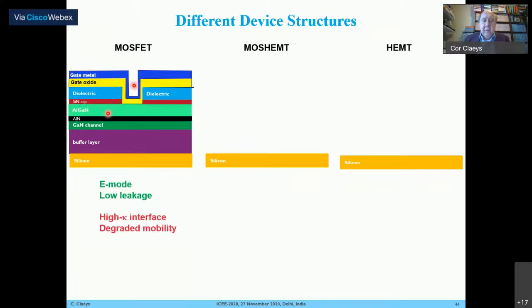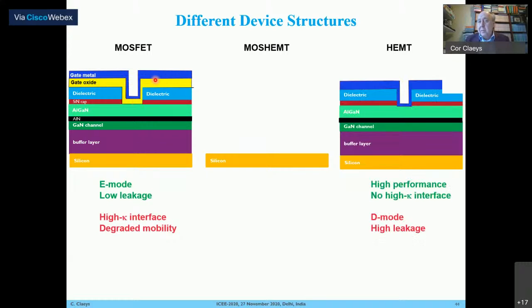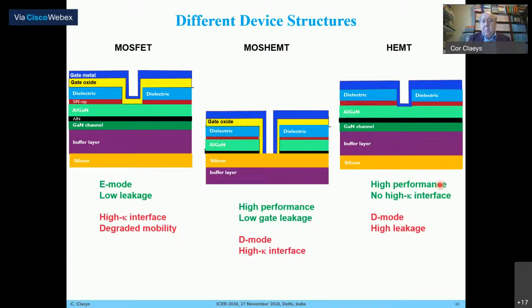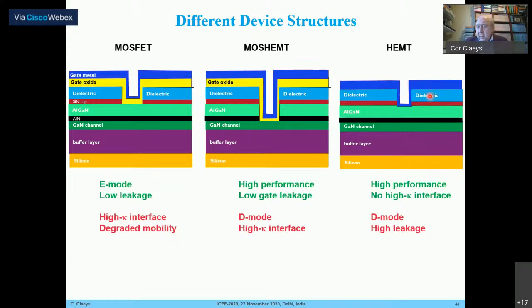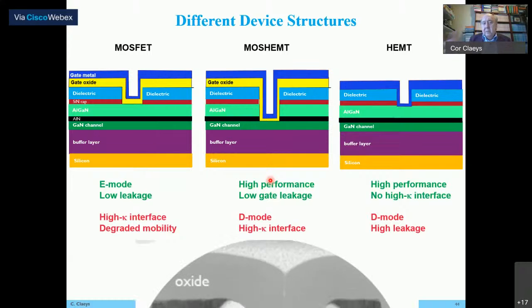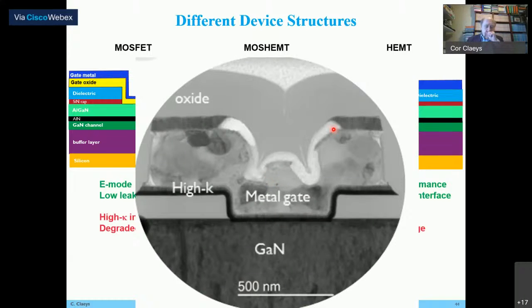You can work with a MOSFET, where you have the standard gate dielectric. You can work with a high electron mobility transistor. There you don't have a gate dielectric, but you have a depletion mode device. That means the device is normally on, and you have to apply a voltage to switch it off. However, you get high performance. Or you can do a combination of the two, depending how deep you're etching, whether you're stopping on the aluminum gallium nitride layer, or you're going deeper, and whether or not you're using a gate oxide. But you can make what we call a MOS-HEMT. This is still a depletion mode device, but with high performance and a low gate leakage. And here you see a very nice TEM picture of a MOS-HEMT.